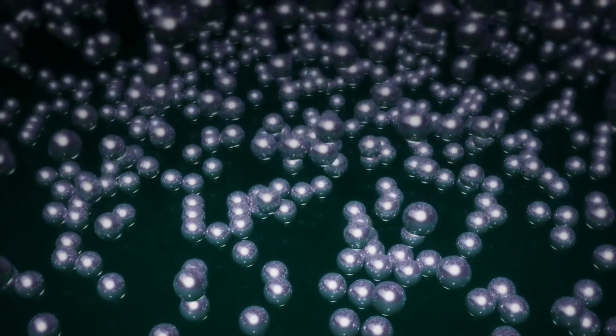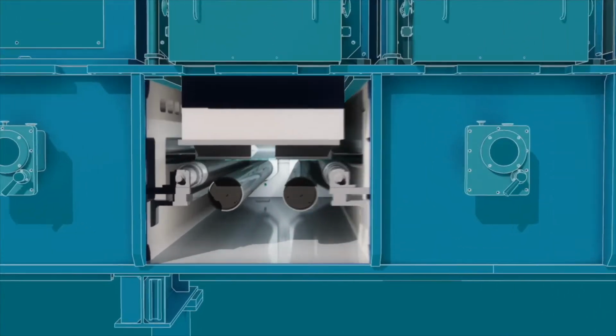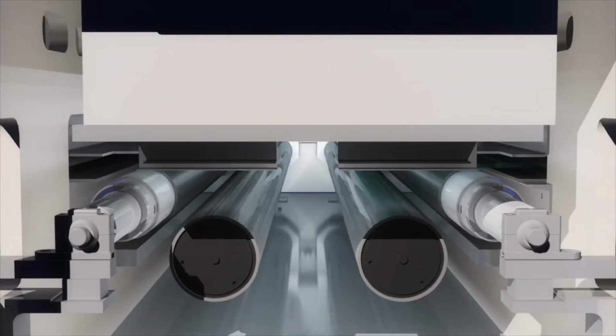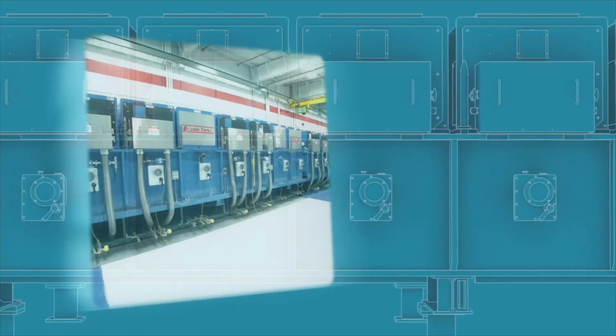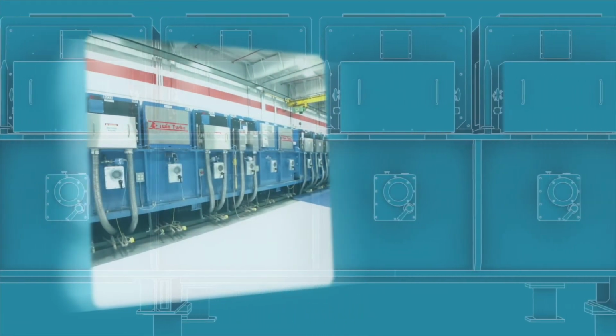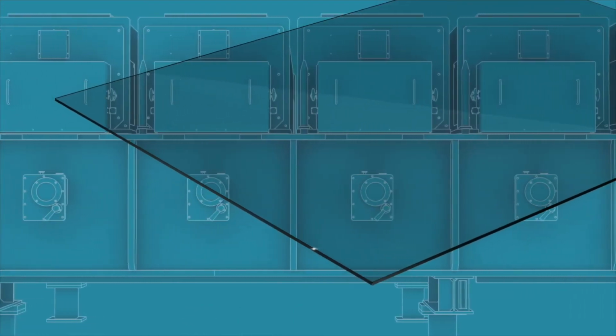Next up, as part of our Stay Clean technology, a sputter process is employed. This means that the titanium-based target is located below the glass pane, providing an even layer to the outside glass surface. After running through the coating line, with all of our layers applied, the complete coating stack is no thicker than 1/10,000th the thickness of a human hair.